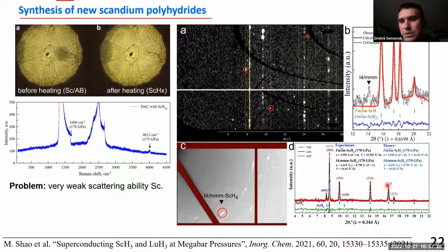It's a series of strong Fm-3m-like diffraction peaks. And as an impurity, we synthesized a compound which should be attributed to tetragonal scandium H4. This compound was missed in the interpretation of this Inorganic Chemistry paper. But when I repeated this experiment with scandium, we got an absolutely similar pattern and similar impurity here. And it can very well be explained by scandium H4. It is a tetragonal structure similar to lanthanum H4 and yttrium H4, and we were able to synthesize it, and the cell parameters are very close to the theoretically predicted parameters at 170 GPa.